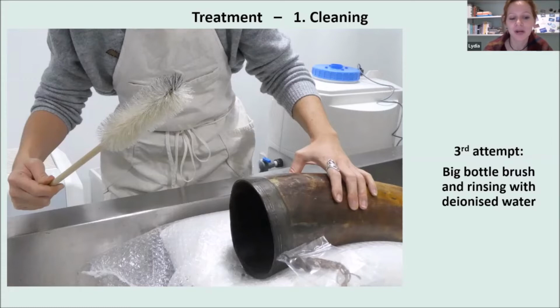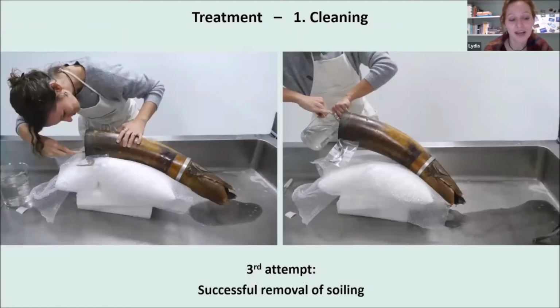I moved the horn to our sink and addressed the encrusted dirt with the biggest brush I could find, while rinsing the interior regularly with deionized water. Black water ran out on the other end, and when the water started to become clear, I used a toothbrush to address the dirt in the more vulnerable areas, such as the crevices and the laminating layers. This procedure cut the cleaning time from, I would say, possibly 2 months to 4 hours.